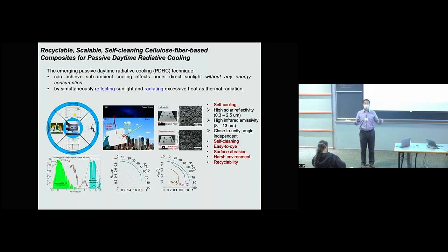If any surface could re-emit energy between 7.8 and 13 microns, this energy can simply go through the Earth's atmosphere and get lost to the ambient. This is only the first window; we also have several other windows, maybe between 20 and 22 microns, and also at even longer wavelengths. But most research simply focuses on the first window of the Earth transmission, between 8 and 13.